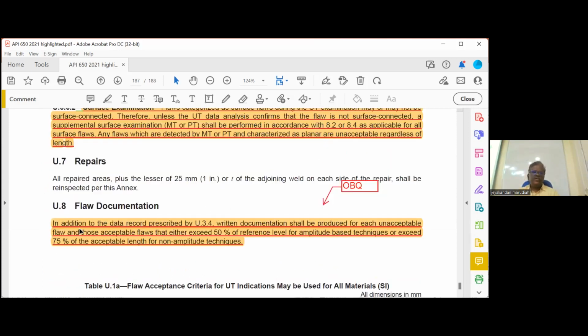This is the flaw documentation. In addition to the data, written documentation shall be produced for each unacceptable flaw, and the acceptable flaws that either exceed 50% reference level or 75% of the non-amplitude technique.